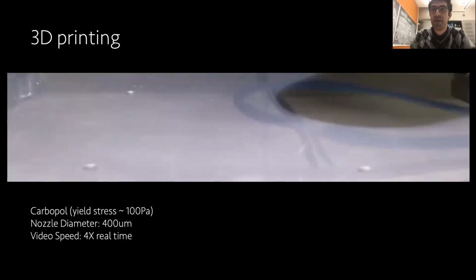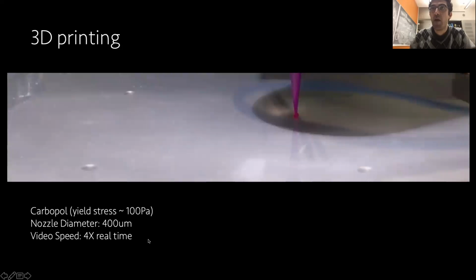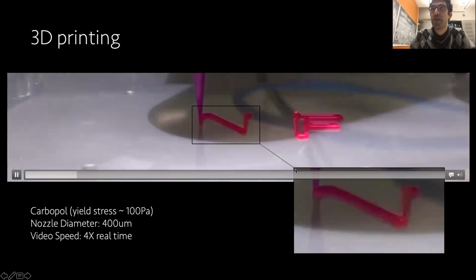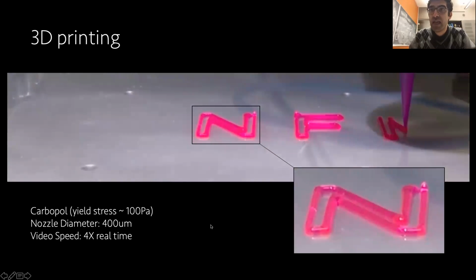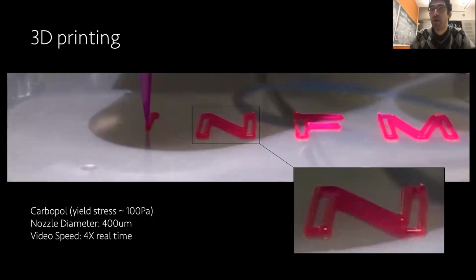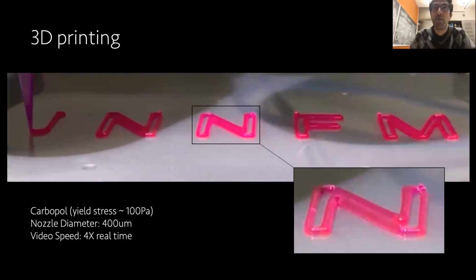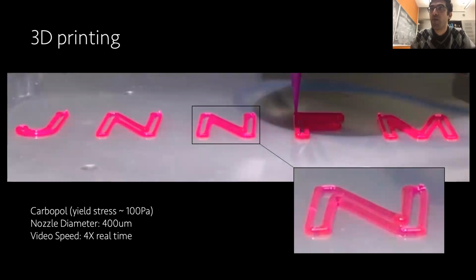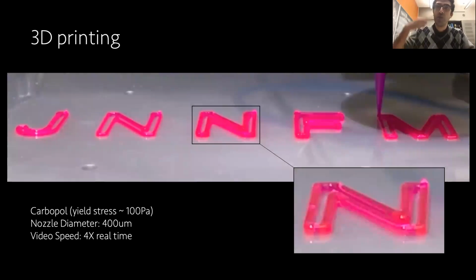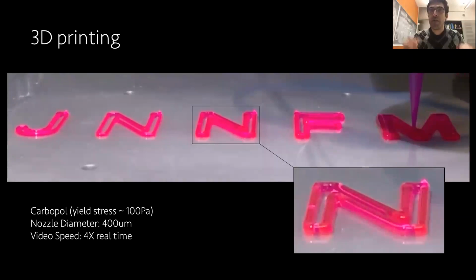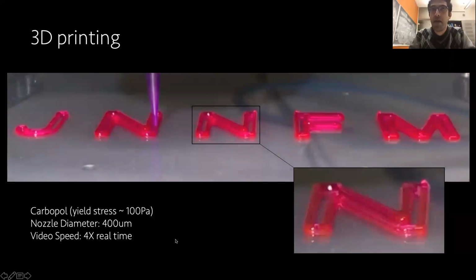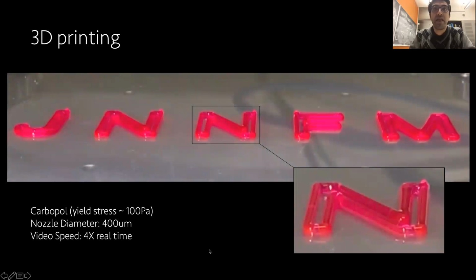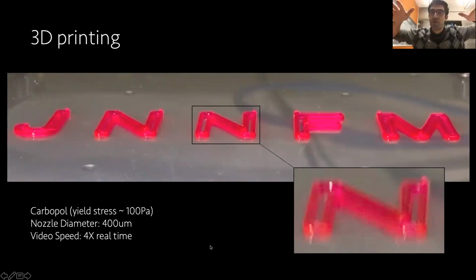So here is an example that I did just last week. My material is Carbopol, with a small nozzle diameter, and this is sped up. This is my nozzle printing something. I'm zooming in here. This is the first layer on top of my plastic, in this case actually a deformable surface. After the first round is over, I start printing the second round, and you keep doing this. And if you have suitable materials, you can print in 3 dimensions. It's a relatively elegant science. What happens is that you spread this material on the substrate, and then spread the second layer and the third layer on top of the liquid.